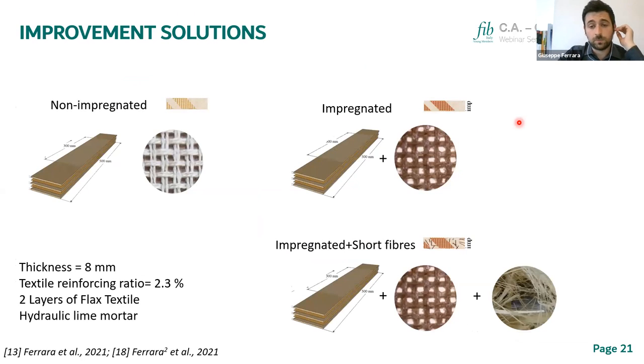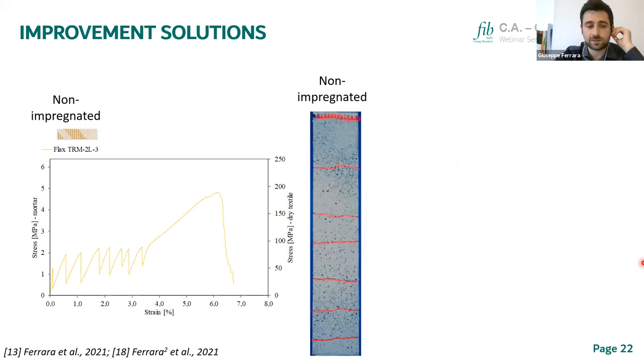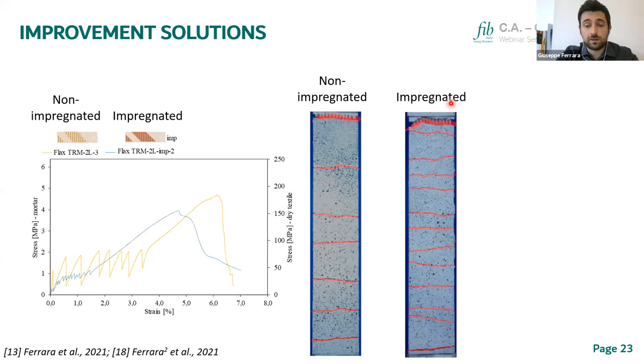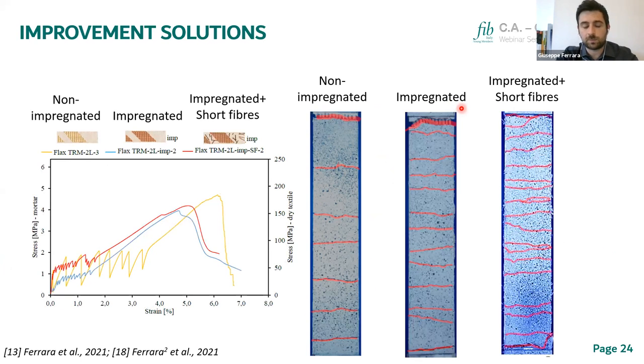Well, if we go quickly to the results of this research, we can see very promising results. We have basically three series of specimens: the reference one with non-impregnated flax textile; a series in which impregnated flax textile was adopted; and a third series in which both impregnated textile and short fibers within the mortar were used. The three series of specimens were characterized by two layers of flax textile. If you look at the stress-strain response of a representative specimen of each series, this is what we have already seen for the reference non-impregnated series before. We also have a crack pattern on the right side. This is a representative specimen of the series in which impregnated fibers were adopted. And this is a representative response of a specimen with impregnated fibers as well as short fibers.